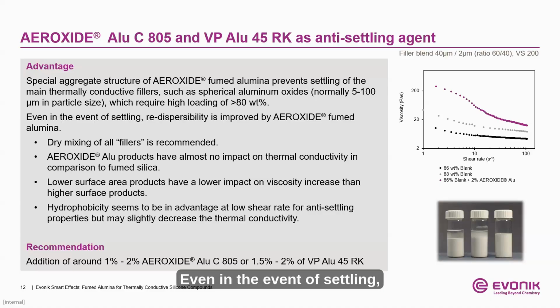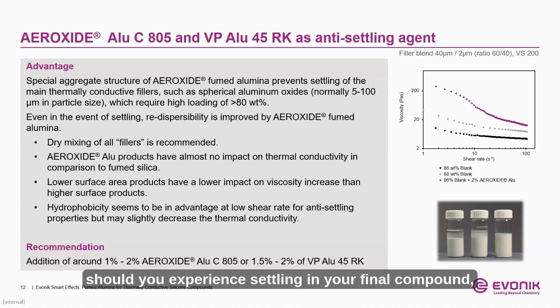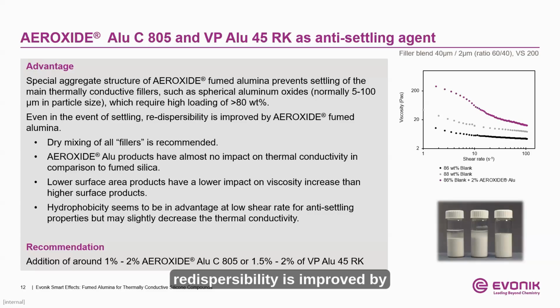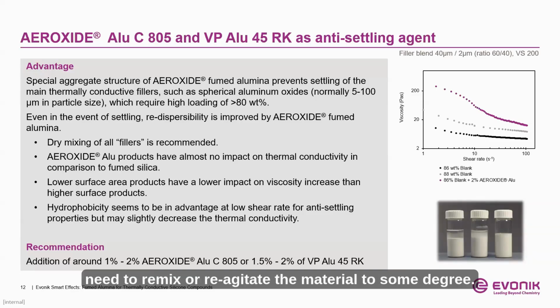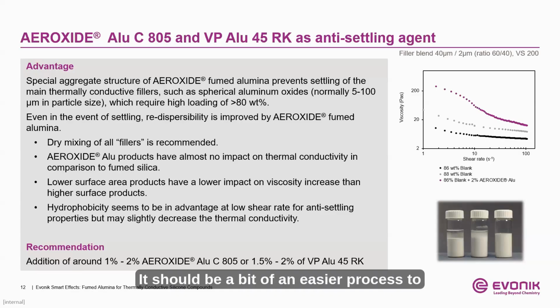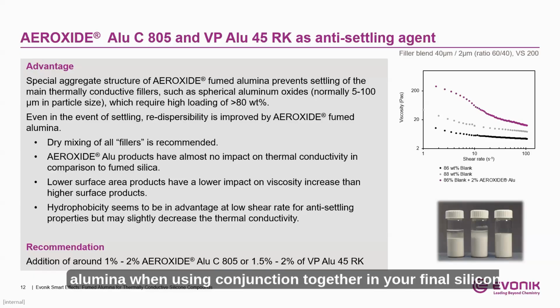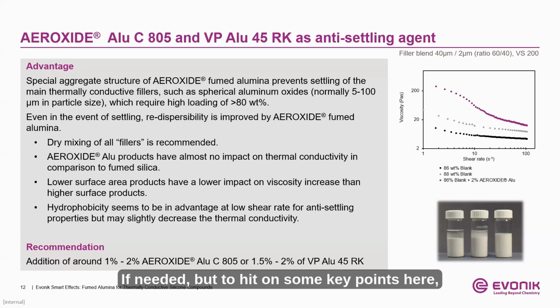Even in the event of settling, should you experience settling in your final compound, redispersibility is improved by addition of the AEROXIDE fumed alumina, meaning it would be easier if you did need to remix or reagitate the material to some degree. It should be a bit of an easier process to reincorporate and redistribute the spherical alumina as well as the fumed alumina when used in conjunction together in your final silicone compound to really rehomogenize everything in an efficient way if needed. But to hit on some key points here, dry mixing of the fillers is recommended.